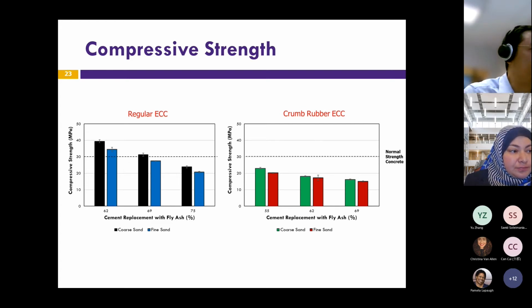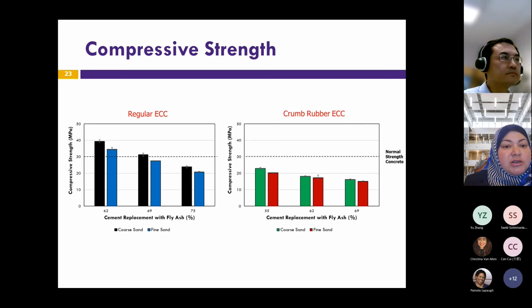As you can see here, the ECC has different contents of fly ash, and it also has coarse sand and fine sand. We found that the ECC with the coarse sand exhibited higher compressive strength as compared to the ECC with the fine sand. This was the case for both cases, the regular as well as the crumb rubber ECC. As you can see, the compressive strength was drastically reduced by using the crumb rubber, which is expected due to poor bonding between the cementitious matrix and the low stiffness of the crumb rubber.